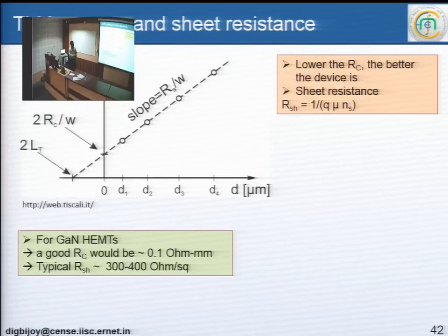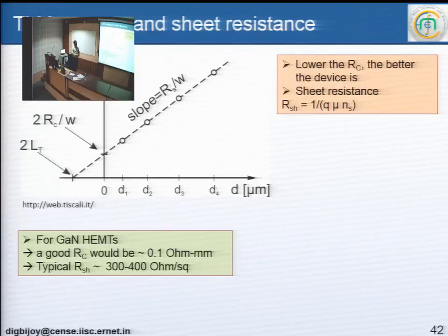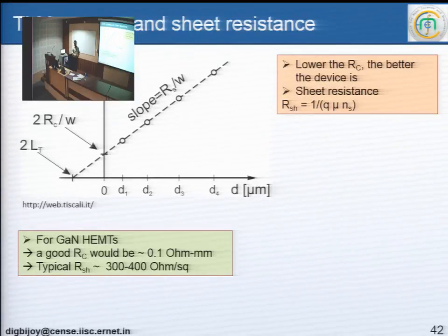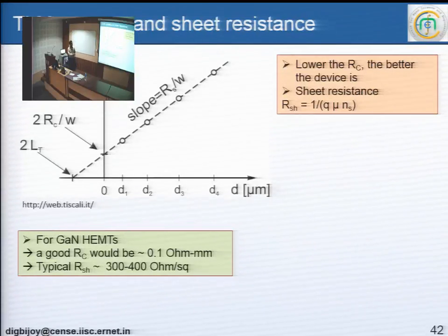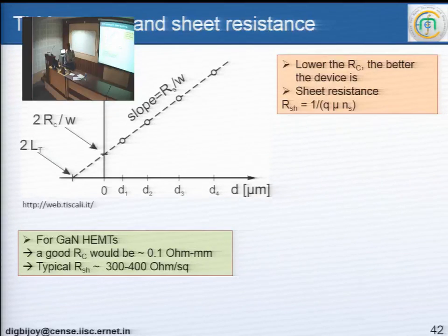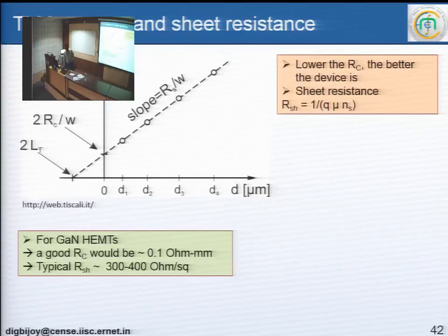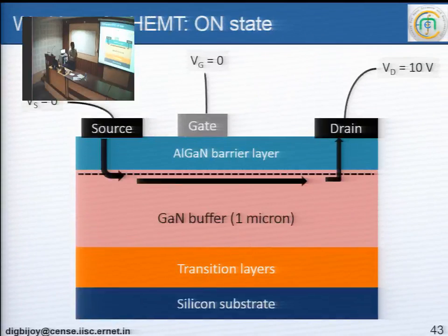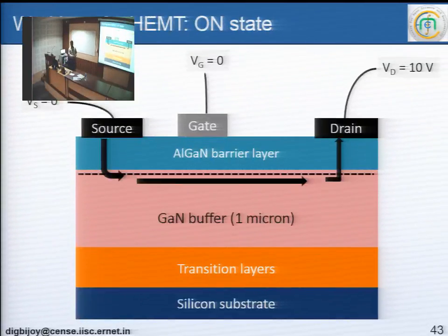So for example, in gallium nitride, a typical good contact resistance would be around 0.1 ohm millimeter, and a sheet resistance would be between 300 to 400 ohm per square, for example. So this is the first important thing that one should do when you get a transistor wafer. Now this is again a schematic of a gallium nitride transistor, for example.